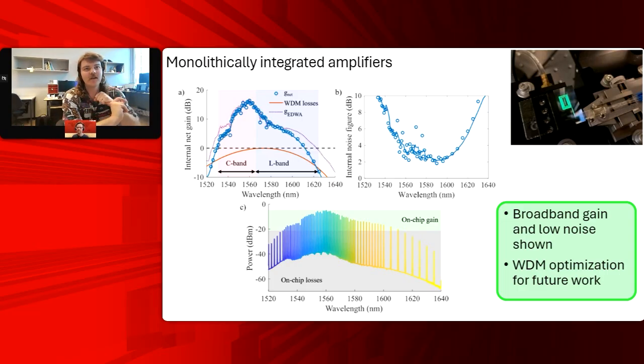We can get lower losses with it as a bare host, but for these erbium sites that are inside, we do some preliminary XRD measurements to measure this crystallinity and see how heat treatment can affect the host material. It's a very delicate interplay. This is a very good question. And if I wasn't in such an application-specific, hardcore gain measurement phase, I would have spent my time here at University of Twente doing this kind of delicate spectroscopy, XRD, and high-resolution TEM images to see these sites and tease out where they're sitting in the host material. But this is the next frontier of science.